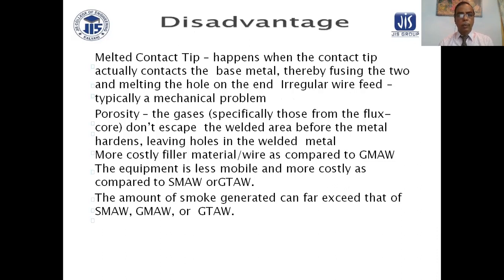Disadvantages: a melted contact tip happens when the contact tip actually contacts the base metal, thereby fusing or melting the hole, or from irregular wire feed, typically a mechanical problem. Porosity: the gases, especially those from the flux core, don't escape the welded area before the metal hardens, leaving holes in the welded metal. More costly filler material as compared to gas metal arc welding. The equipment is more costly as compared to SMAW or gas tungsten arc welding. The amount of smoke generated can far exceed that of SMAW, gas metal arc welding, or gas tungsten arc welding.